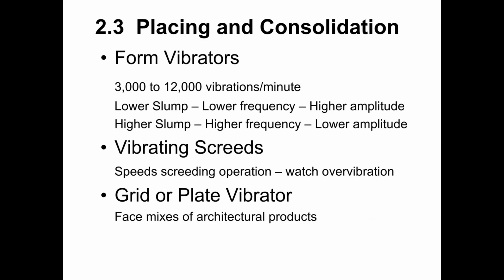Once the form was set on the shock table, they would activate it and it would physically lift the form and then drop it. This is a good example of low frequency, high amplitude vibration. It was low frequency. You could actually see the shock table going through a cycle of lifting the form and dropping it, lifting a form and dropping it. It would go through a cycle of maybe 1 per second. It was high amplitude because you could actually see the displacement of the form. It would be lifted several inches and then dropped several inches. So that's low frequency, high amplitude vibration.